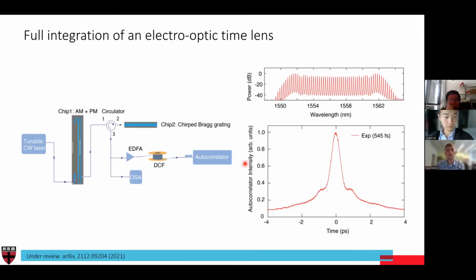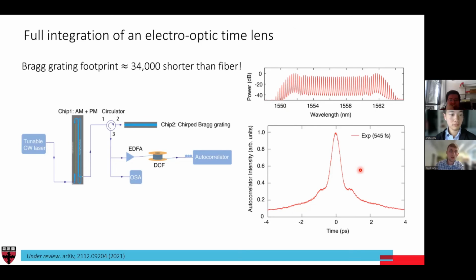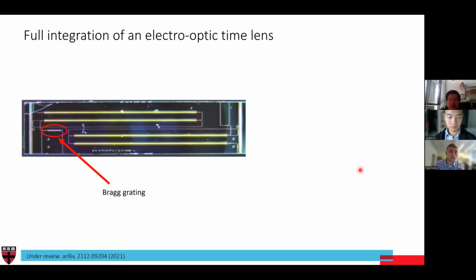And so we found the optimal design for this, and in this case, on 2 different chips, we're able to fully compress our laser pulse to 540 femtoseconds. And the size of this grating is about a factor of 34,000 shorter than what you would have in your single mode fiber. And so what this means is that we can fit all of it on a chip.